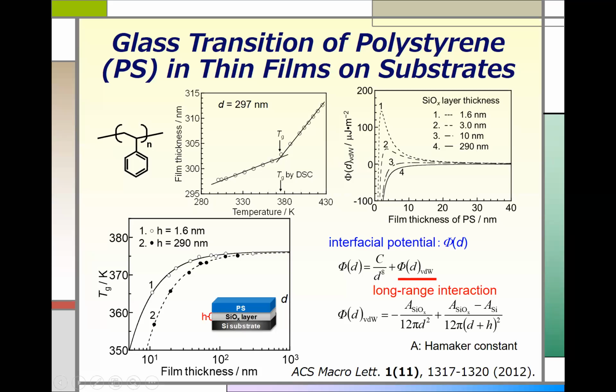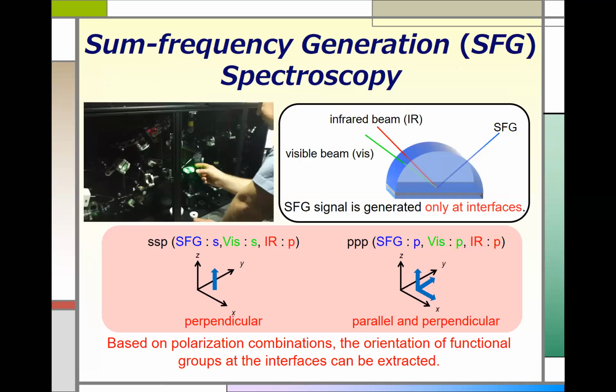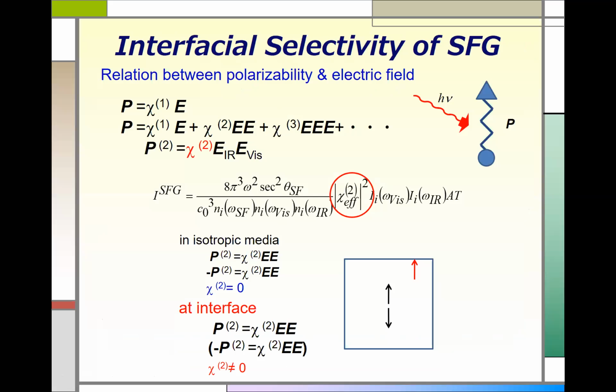So then we're going to really take a look at the polymer structure at the solid interface. How we can do that is to use sum frequency generation spectroscopy. This is like a vibrational spectroscopy, infrared spectroscopy. This is almost the same as IR, but the difference between conventional IR and SFG is the depth resolution. In the case of SFG, the depth resolution is better than 1 nanometer. It's completely molecular level. And actually here is the principle, but I'm sure that chemistry people don't like equations, so let me skip this part. But the point here is that, as I told you, this technique is really interface sensitive. And one more point we have.